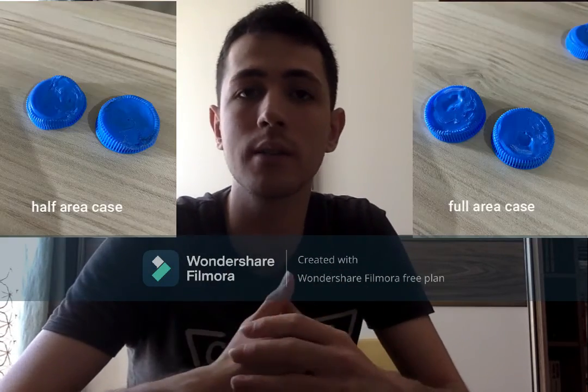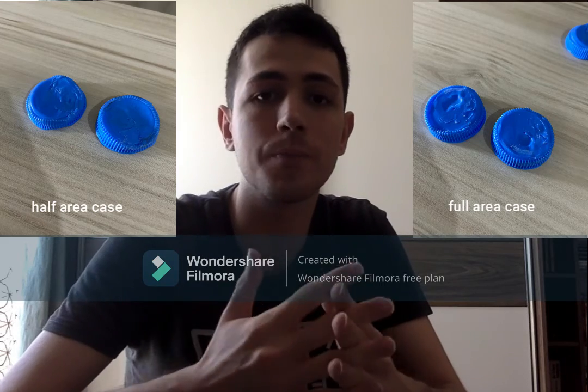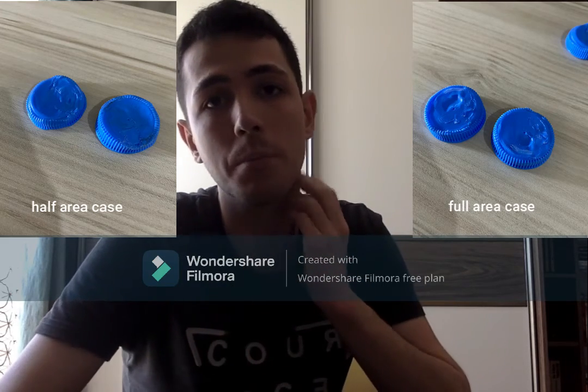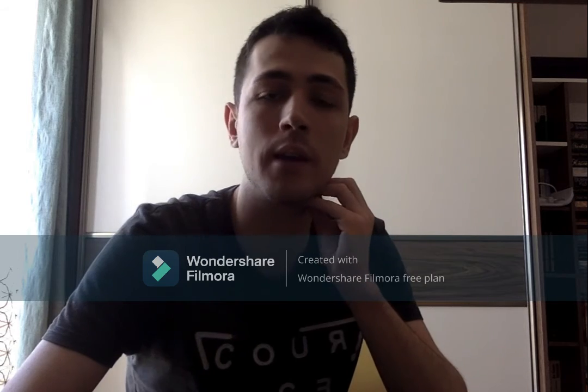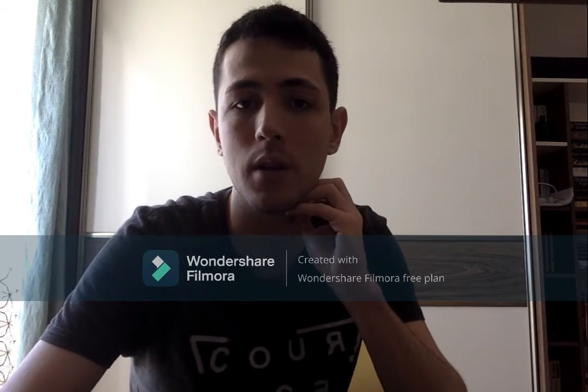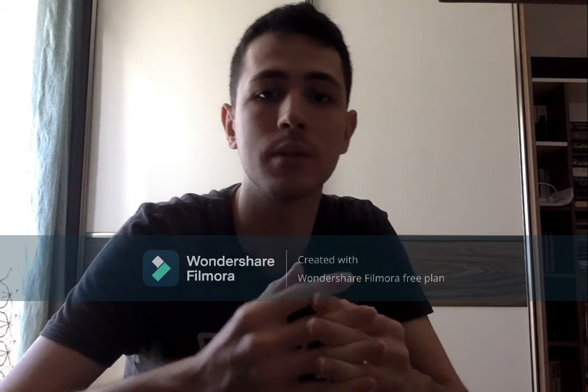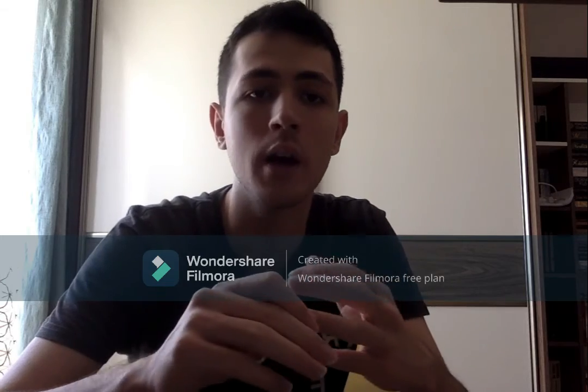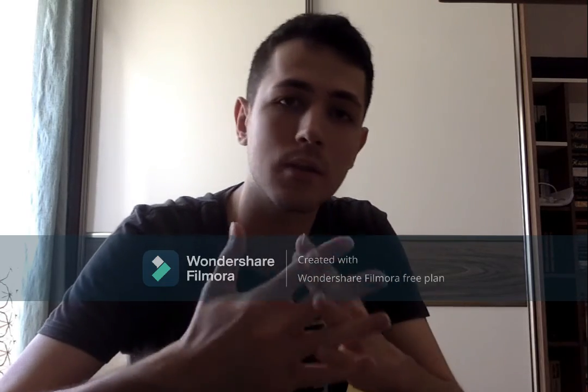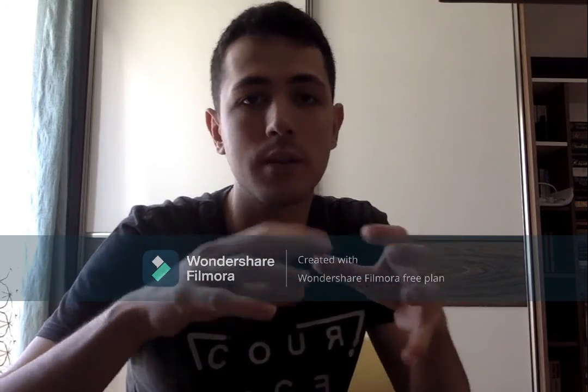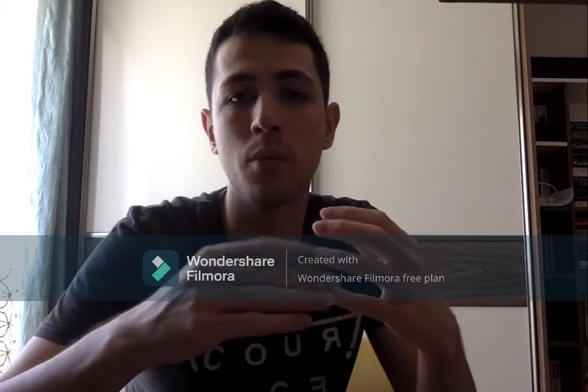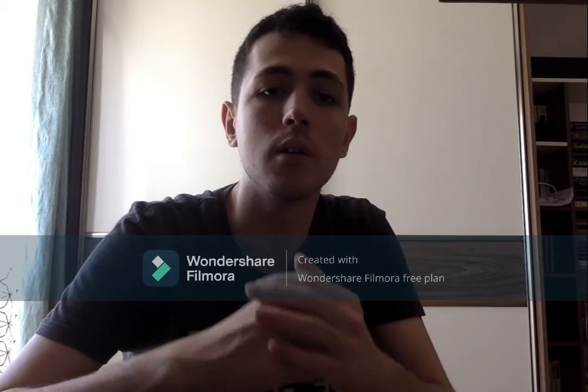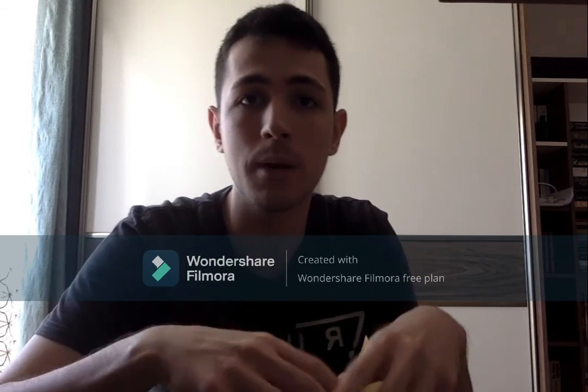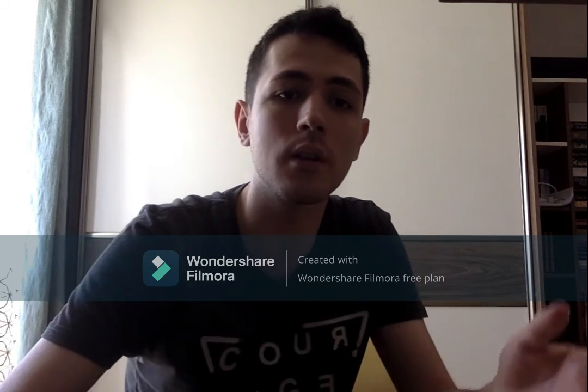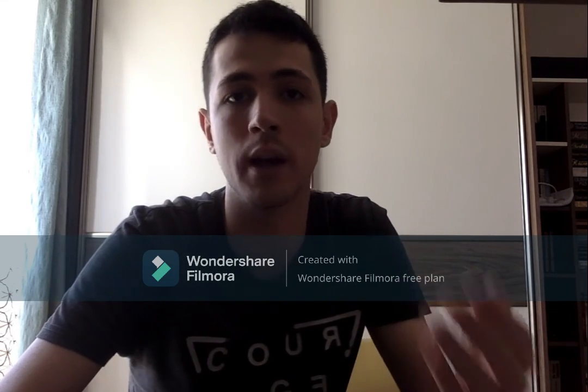Let's have a look at the lid surface after the separation. Bonding marks on the lids and interface surface are remarkable. The full area case specimens have a larger fusion bonding area, whereas half area case specimens have a relatively smaller fusion bonding area as expected. It can be concluded that the experiment is consistent with the theoretical relationship between welding area and welding strength.